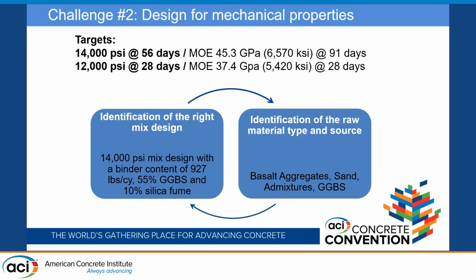So for these designs, the cement was coming from LafargeHolcim in the Kanthan plant in Malaysia. The slag, which was critical to the packing density and the gradation, was coming from Rizhao, China. The silica fume was Elkem Asia out of Thailand. And that material proved to be better than the local material because it had better consistency. And then again, the key to the success of this project was the basalt aggregate, about 125 miles from the project, so it had to be imported. That's a lot of material to be imported, but it was critical to the success of this project.